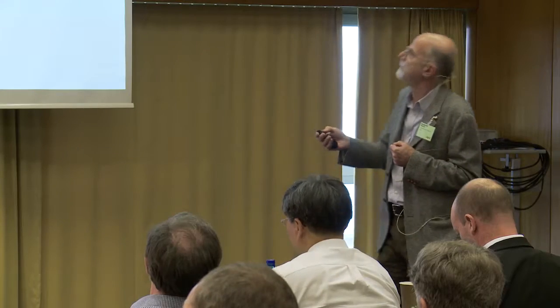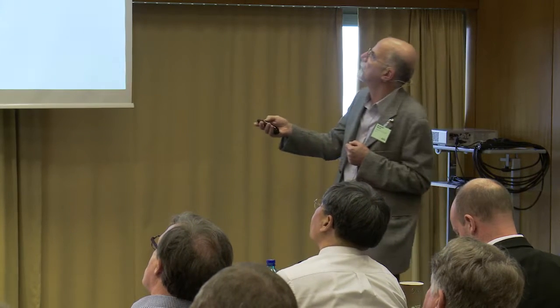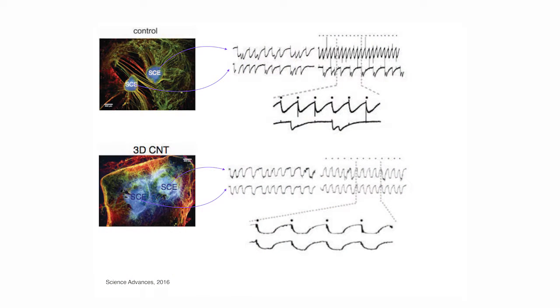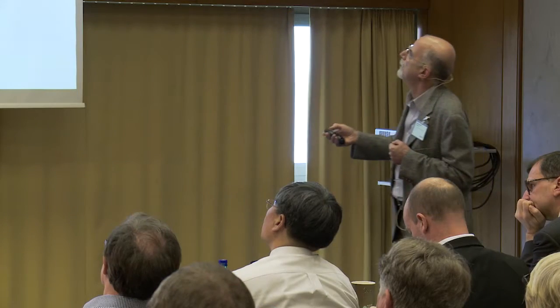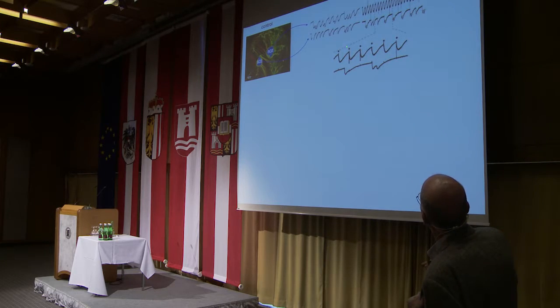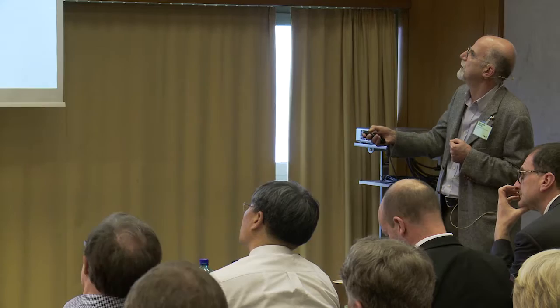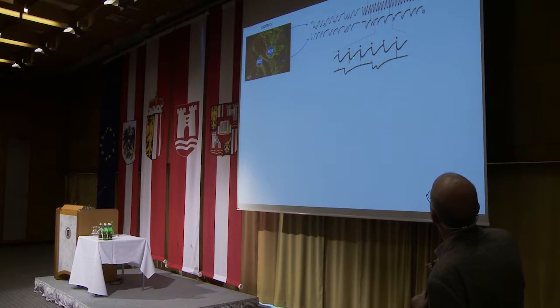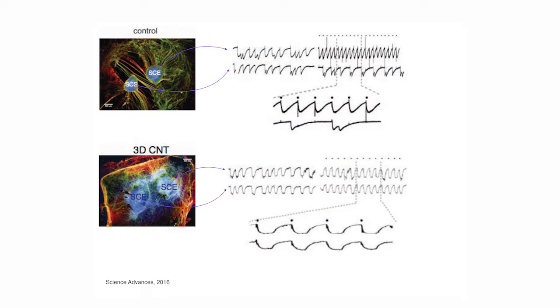So now the electrophysiology. Basically, when we have the two slices, we see this is the spontaneous activity. These are the electrical signals that each spinal cord explant sends spontaneously. And we can see that they are not coordinated at all. So each slice is completely independent. If we try to stimulate one of the two slices, for instance this one, with continuous regular pulses, we see that the other one doesn't respond at all. So this is an enlargement. You can see these are the pulses. So the first slice responds in this way, but the other one completely ignores the electrical stimuli.